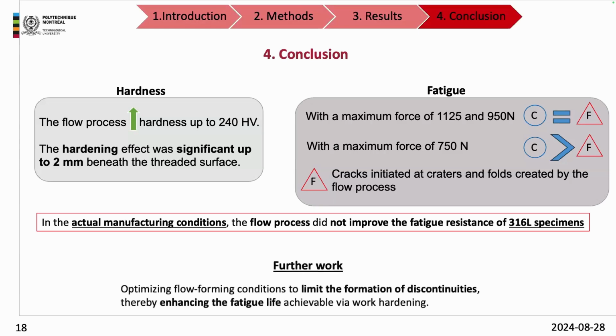But we can suggest further work because the main reason why we didn't improve the fatigue life was the presence of those discontinuities. And since those discontinuities are manufacturing process dependent, we can work on the manufacturing parameters in order to reduce or avoid, in a perfect world, the presence of those discontinuities, and thus take advantage of the work hardening induced by these processes.